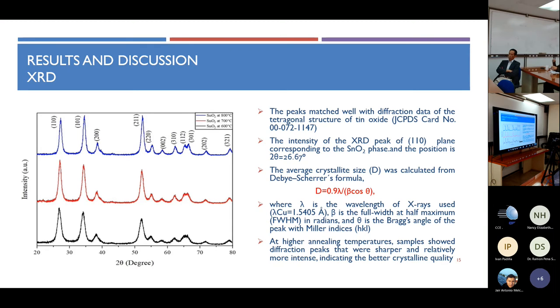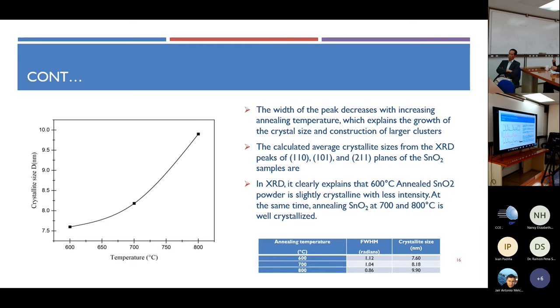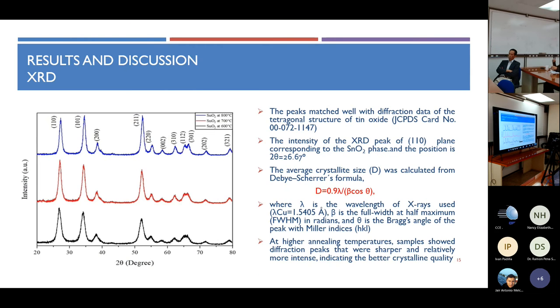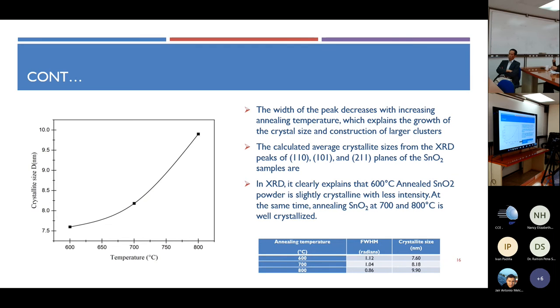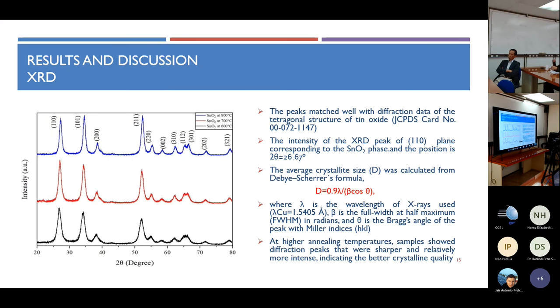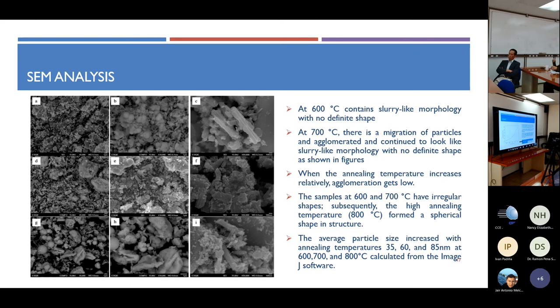And the crystalline size is calculated using the Debye-Scherrer equation. This is a graph showing the crystalline size increases when increasing the temperature. I used the three important peaks, 110, 101, and 211, took the full width at half maximum and calculated the crystalline size using the Debye-Scherrer equation. You can see clearly that 600 degrees Celsius is less crystalline, while 700 and 800 degrees Celsius show a highly crystalline sample. From this XRD, we can understand that.